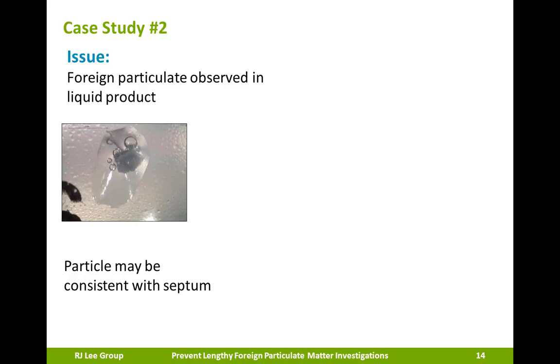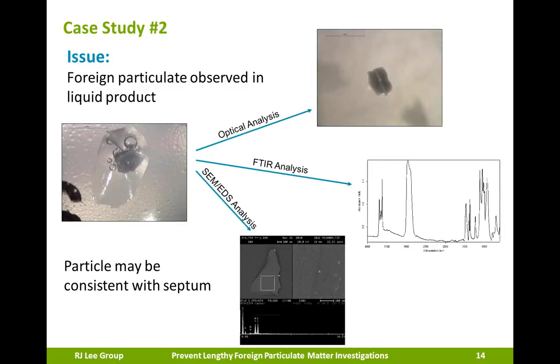In the image, you can see the particle kind of stuck to the side of the vial here, encapsulated in the product matrix. So we extracted the particle from the product, rinsed it with water, and prepared it for the forensic analysis. An optical image was collected once we isolated the particle. The stereomicroscopic evaluation revealed a particle that was gray, and it measured approximately 700 micrometers in length. When probing the material, the observation of it being soft and rubber-like was recorded. FTIR analysis was performed and the spectrum you see was obtained.